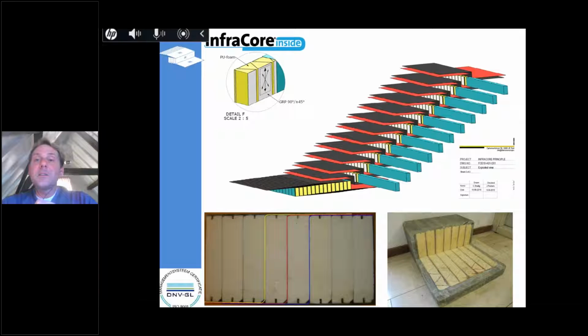So this is, I think, the best illustration of our technology, where you have these overlapping layers, which enables us to avoid this global crack growth propagation, which would lead to delamination. We can add webs in every direction as deemed necessary, and we can make structures going from, let's say, a height of 4 centimeters all the way up to what we did actually already. We could go further, but we went already to structures with a height of 3 meters. So we can make very slender products, but we can also make very high products.